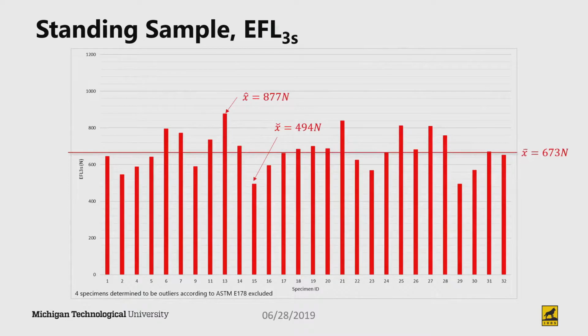And then we did the straight up and down. In this case, we got about 670 newtons, so that was an increase. If we based all of our fracture data, or our strength data, on the standing sample, this would indicate that the samples were actually stronger than they would have been if we were just isolating that one edge. And remember, for structural glazing scenarios, we may not always have perpendicular loads passing through our elements. We need to be able to handle loads and stresses coming from different directions and orientations.